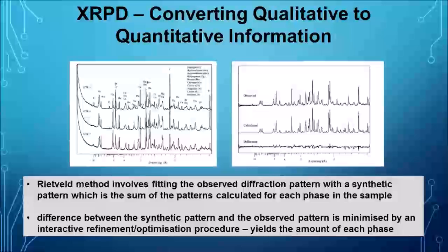The first thing we did was to powder the material and carry out X-ray diffraction analysis. The traces here on the left are examples of COPR from 3 different sites. So it's 3 different traces, but there are very common features occurring in most of them. We go to a database to start to work out what the various peaks might be. In some cases, we had to look a bit further afield to identify some of the minerals, but many of these we did find in standard databases.